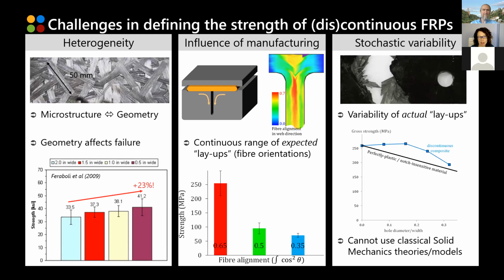Now, the image that you are seeing actually represents the gauge section of the specimens that we have used before to measure the strength, let's call it that, of these materials. And you can see that clearly we have a microstructure that interacts with the scale of the geometry. And for instance, if we think about ASTM standards for testing the tensile strength of composites, and in particular the tensile strength of discontinuous composites, they actually recommend that we use only half of the width of what we have here in this specimen.